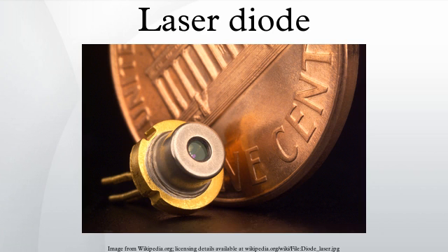The reflectors at the ends of the cavity are dielectric mirrors made from alternating high and low refractive index quarter-wave thick multilayer. Such dielectric mirrors provide a high degree of wavelength selective reflectance at the required lasing wavelength λ if the thicknesses of alternating layers D1 and D2 with refractive indices N1 and N2 are such that N1D1 plus N2D2 equals λ/2, which then leads to the constructive interference of all partially reflected waves at the interfaces. But there is a disadvantage. Because of the high mirror reflectivities, VCSELs have lower output powers when compared to edge-emitting lasers.